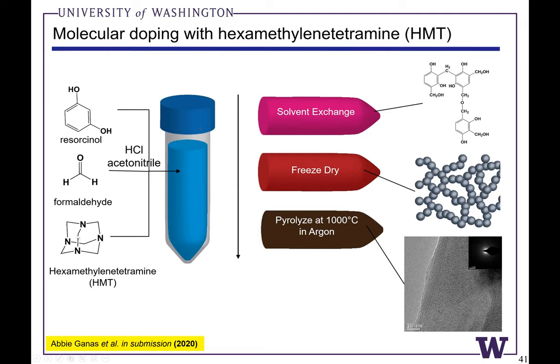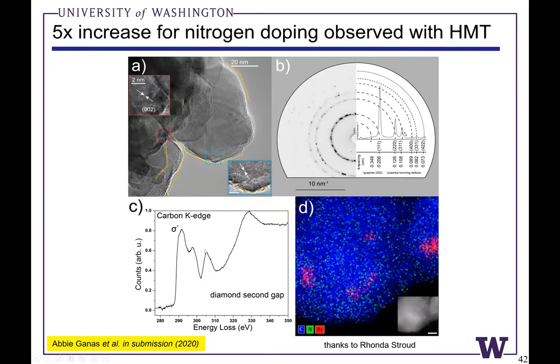It's a batch reactor. Abby will add a range of different concentrations of hexamine to the organic starting materials and go through the same process, pyrolysis. And was asking the question, can we increase emission from nitrogen vacancy defects in diamond? So Abby's done a really wonderful job in this project.